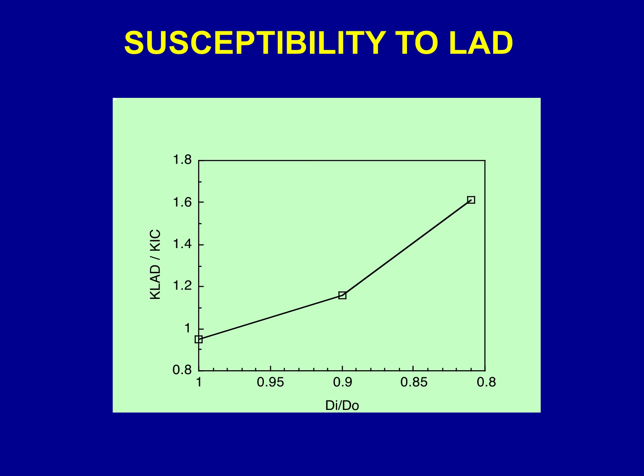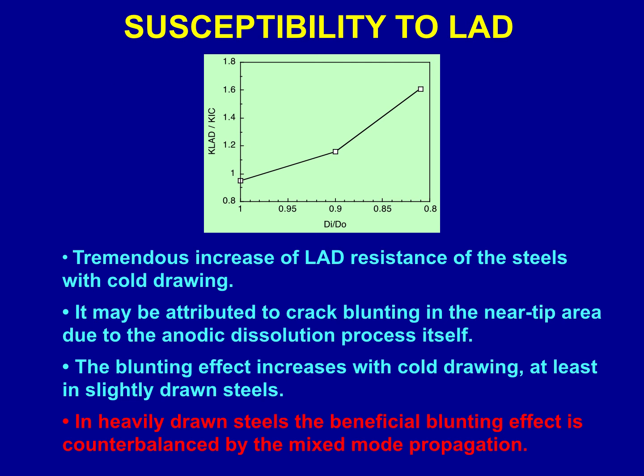The discussion of these results with regard to the susceptibility to localized anodic dissolution has a surprise. We have the critical stress intensity factor in aggressive environment, K-LAD, localized anodic dissolution, divided by K1C. It is an increasing function of the cold drawing degree, the ratio of diameters. Why? There is a tremendous increase of localized anodic dissolution stress corrosion cracking resistance of the steels with cold drawing.